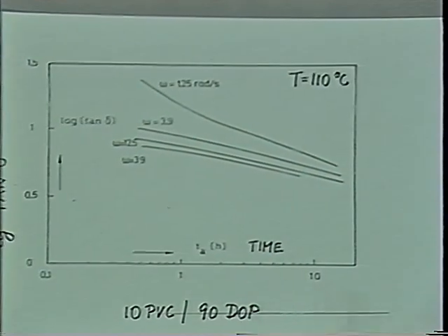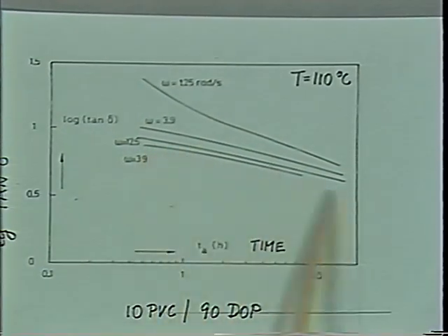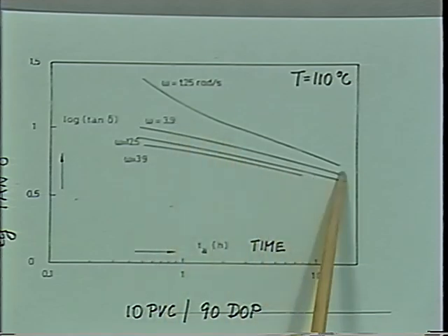of data. He also performed experiments with the same system by cooling down not to 90 degrees, but to 110 degrees. And then he followed the evolution of tan delta, realized that tan delta at different frequencies is going kind of parallel, approaching each other, but then it's staying parallel.